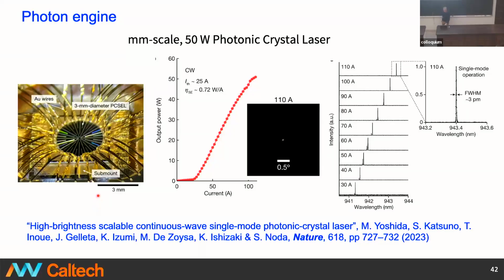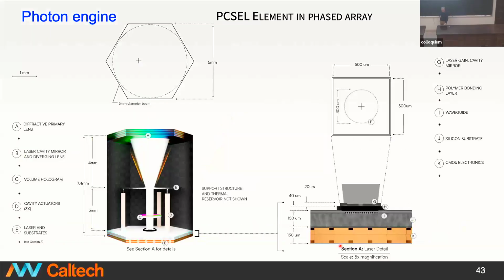So he managed to develop a photonic crystal laser that is hundreds of microns in size in aperture that lases in a single mode with a power of 50 watts. So it's really quite a remarkable laser. It's a very high beam quality, very narrow line width, very narrow divergence. And it's the basis for the laser elements in this dense laser array that we developed as a design for Starshot. They use these photonic crystal lasers and disperse the beam so we have relatively uniform illumination.